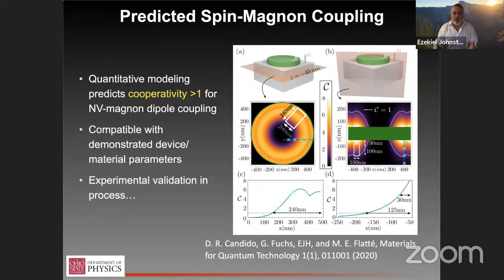So a cooperativity of 1 is the minimum threshold for being able to read out or write quantum information to a system. And what we're looking at here, which I probably should have said at the beginning, at the top of the slide, is the spin-magnon coupling. So if I have an NV center somewhere in the bulk of this diamond, and I flip it to change its quantum state, that can then excite a magnon in the YIG disk. And so the cooperativity measures the fidelity with which we can do that.